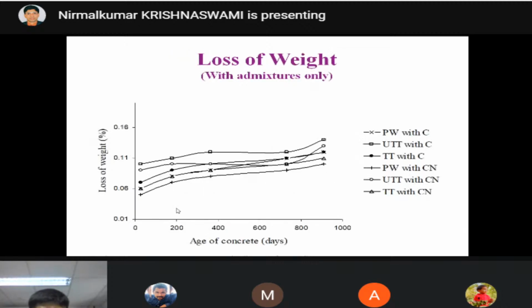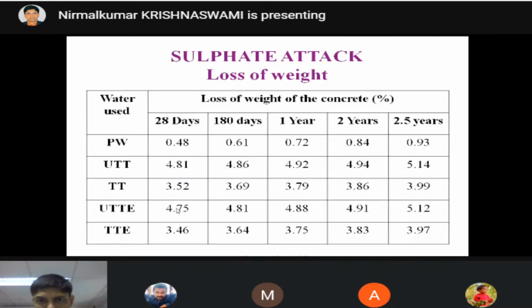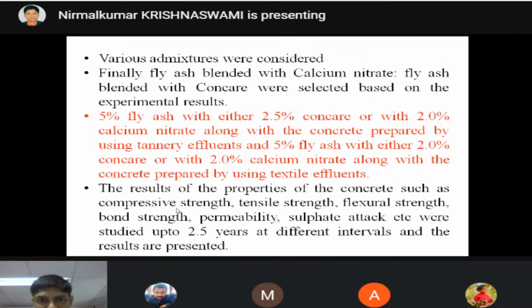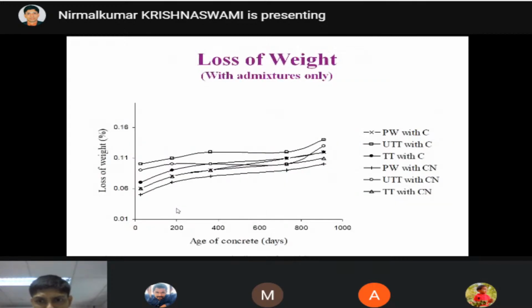Just when I am adding the admixtures, calcium nitrate, I mean this Concare at 2.5 percent and calcium nitrate at 2 percent, see, the maximum is only 0.15. This is 0.16, meaning around 0.15. So maximum it is 0.15.